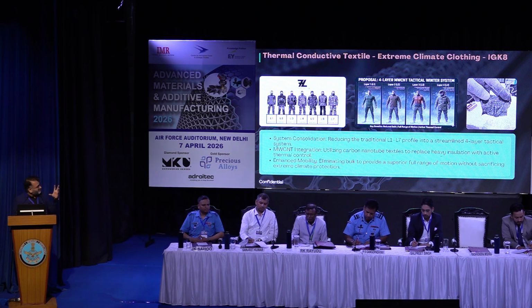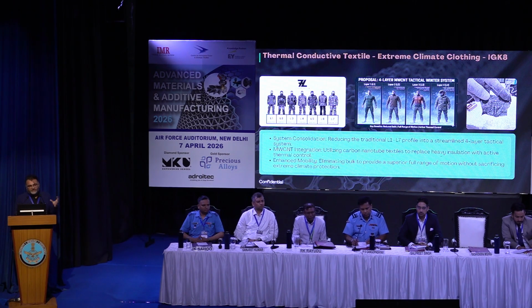As you can see in the second photograph, the third layer is the nanoparticle coated cotton, which with a minimum amount of electricity can give you up to 20 to 30 degrees delta over the environment temperature. With fewer layers and less weight, you can be at a very comfortable temperature. This is already being used or being researched in the US. We offered this to defense and we are working on this project right now for defense through the Ministry of Textile.